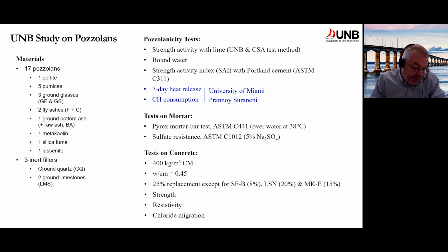So I want to finish by sharing some work that we've been doing at UNB, evaluating a wide range of pozzolanic materials and some examples of inert fillers as well. We've been looking at various different test methods, including the ASTM bound water test method, and our own, a strength activity index we developed based loosely on the old strength activity with lime index that used to be in ASTM. And I want to share some data from these tests with you, and tests on concrete also.